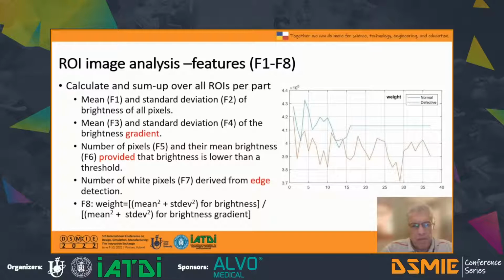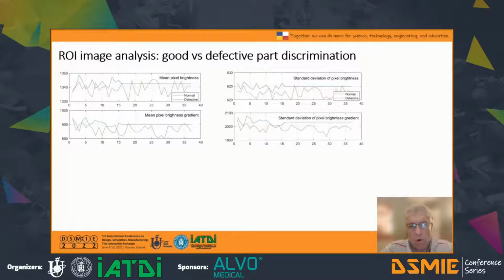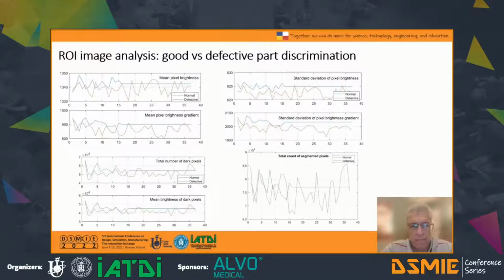Each of these features can be represented for all the parts that we tested by their numerical values following curves. You can see the blue curve here corresponding to a normal part and the red curve for a defective part. So it's clear that the normal part is represented by a curve which is well or mostly above the red curve. This is true for most or all of the other features, and this is important because like that we can differentiate right from the start between good and defective parts. You can see the curves for all the rest of the features.